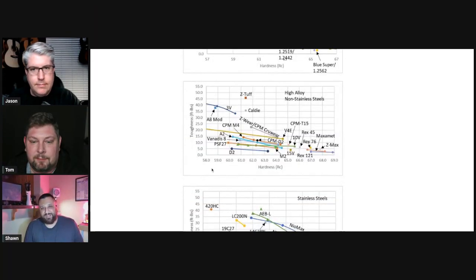It's not necessarily going to always make it tougher than a steel that's maybe an ingot steel, because it's kind of chemistry dependent. If we have less carbide, we're going to have more toughness. But the problem is, if we have less carbide, you're going to have less wear resistance. And for the end user, it means that your working edge is going to blunt completely smooth. When you're cutting cardboard and stuff, it's going to just start sliding and slipping. So the secret is not just dropping carbide volume and making it so I have 1% carbide volume, and then I increase the Rockwell hardness to 65. Now I got the ultimate blade. Well, no, because there's nothing pumping the brakes on the edge from just simply wearing completely smooth.